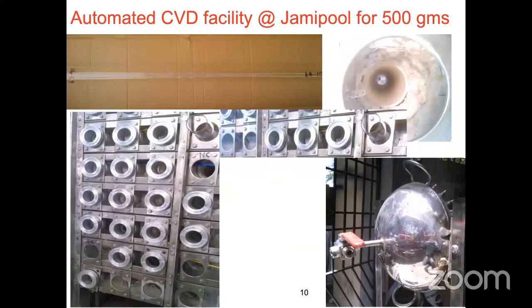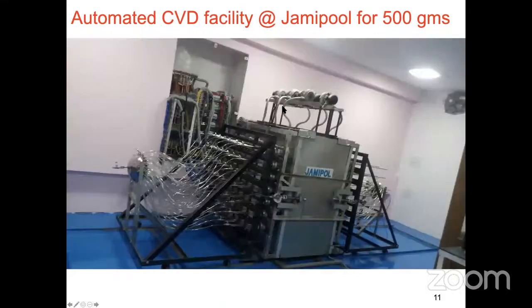So what we have done is that we have the 7x7 matrix of these quartz tubes. You can see the 7x7 matrix. Each one will have one furnace. The entire thing is optimized at the desired temperature, and then you can see the flow tubes, inlets and outlets, through which hydrogen will come. So afterwards, one can get almost half a kilogram of the carbon nanotubes, because each one will make 10 grams, and then we have the 7x7 matrix.